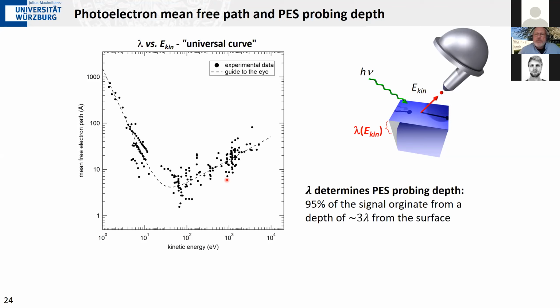And just to give you a feel what this means in practical terms, 95% of the signal that you get out of the sample of the direct photoelectrons that still carry the original energy information come from a depth of 3 times this mean-free path from the surface. Now this turns out to be a number relatively independent of the actual material you're looking at, and that's why this is called the universal curve. This gives you here the mean-free path of photoelectrons as function of the photoelectron kinetic energy. And that, of course, scales a little bit with the photon energy. The higher the photon energy, the faster also the electrons.